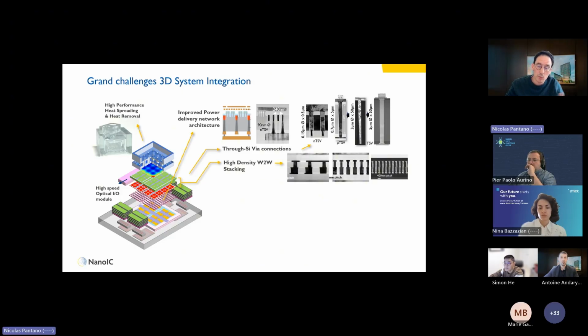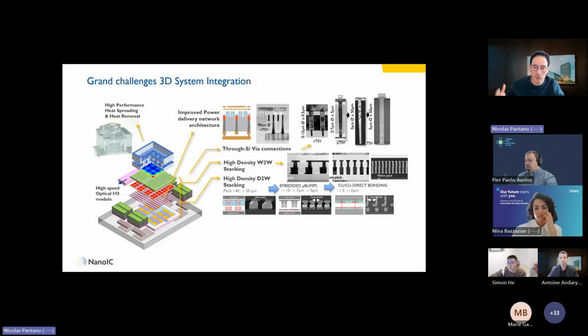At the same time, you want wafer to wafer or die to wafer high density interconnect. This will be helpful in the future to do logic partitioning. So that means that you will distribute your logic compute between two dies and assemble them on top of each other with a high density interconnect. Today, we see pitches in R&D that go for 400 nanometer, even down to 200 more recently, of vertical interconnect between two wafers. But wafer to wafer is good, gets to very fine pitch, but that means that each of the die needs to have exactly the same size. So there will still be systems that have chips that have different sizes, and that needs to be combined in 3D fashion. And that's where die-to-wafer hybrid bonding starts to happen.